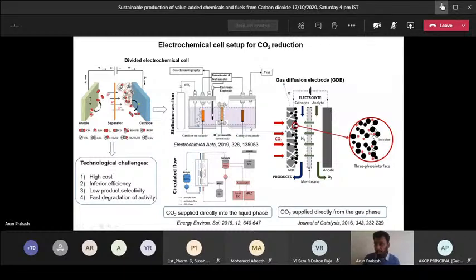So what is the purpose of using these imidazolium cation containing ionic liquids? This can lower your CO2 reduction overpotential, and also it can reduce the energy of the intermediate. And the main thing is there is no water, so it can inhibit HER, and it can boost your selectivity for CO formation. And when you select your electrolyte, you need to care about the concentration of your electrolyte, and depending on the electrolyte, also the kinetics.